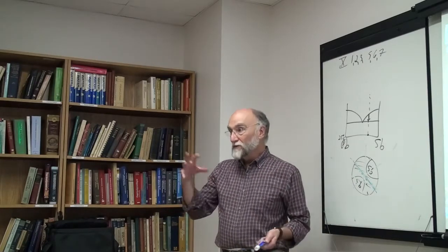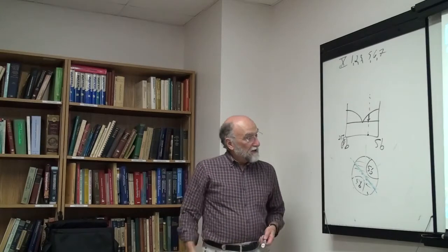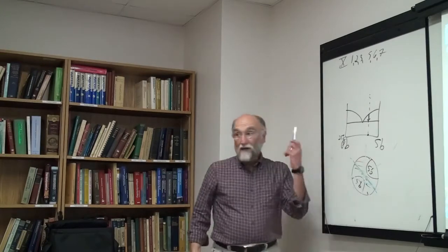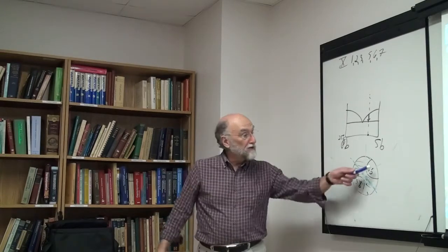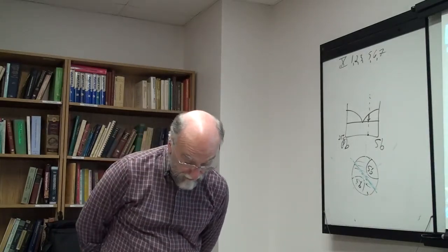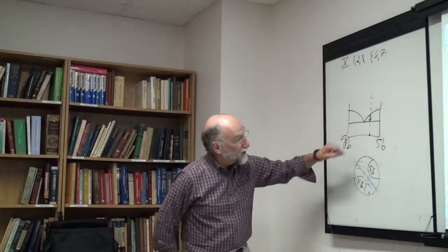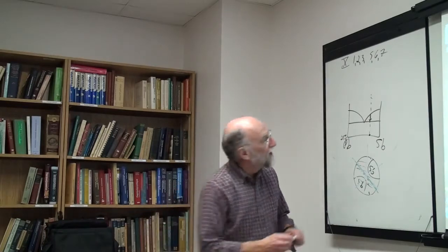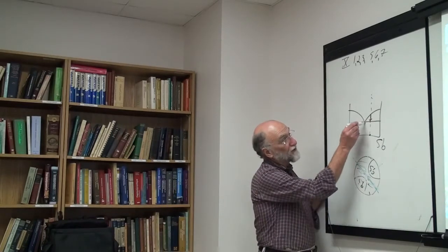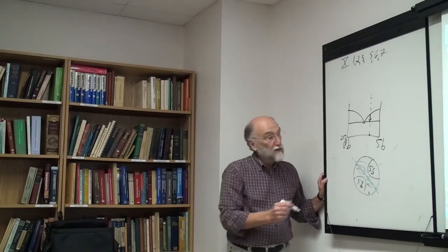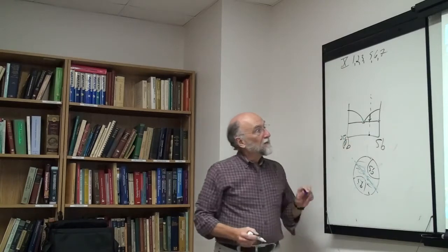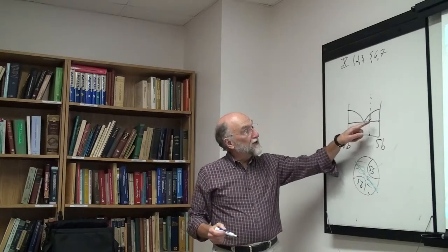Okay, you put this on some sort of image analysis device and it will tell you that 50% of the surface is antimony grains and 50% is pro-eutectic. Okay, so we find that this is by volume, of course. 50% by volume are eutectic grains, which is the two-phase mixture. So remember, the eutectic grains have this composition. The antimony grains have this composition. So 50% by volume is this, and 50% by volume is that.